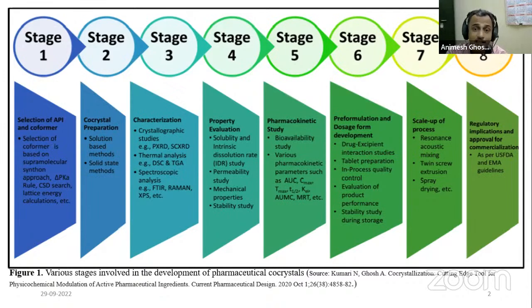During mixing, during milling, and during compression also, because compression has a rearrangement step, right? So there also might be a chance. We need to check every stage where there is a source of breakdown of the crystal lattice. That is very important. For example, which type of granulation technique will we use? Is it wet granulation? If it is wet granulation, then we need to do stability studies, because at higher humidity we need to confirm whether that non-covalent interaction of the co-crystal is breaking or not. After that, we need to do the scale-up process, then regulatory applications.